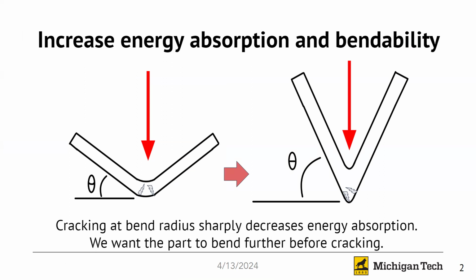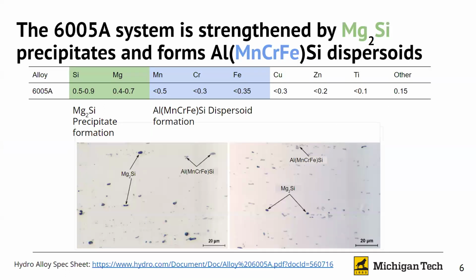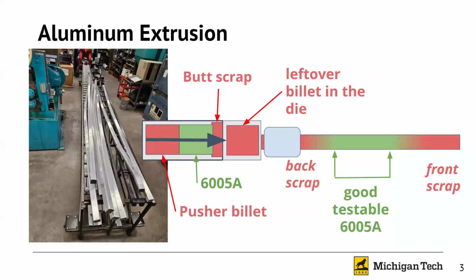Cracking at the bend radius sharply decreases energy absorption. Therefore, we want the part to bend further before cracking. We are looking at 6005A aluminum, which is an alloy that is strengthened by Mg2Si and has aluminum, manganese, chromium, iron, silicon dispersoids to improve extrusion. We cast and extruded our own 6005A compositions to make the bend samples. We use a pusher billet to push out the 6005A billets and use the middle of the resulting extrusion.